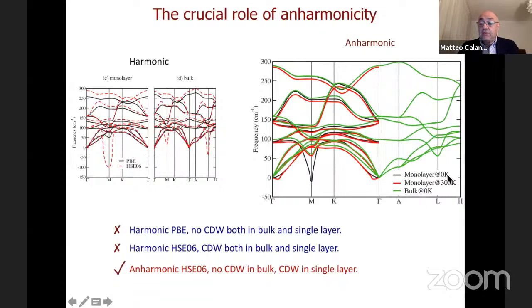As you can see here, the monolayer at 0 Kelvin still has a slightly imaginary phonon, and the bulk at 0 Kelvin has no instability. So actually, the thickness dependence of the charge density wave in the system is entirely due to anharmonicity. So this suggests that the classical theory of Peierls distortion, in which, due to the nesting condition of the electronic structure, you have a strong energy gain by the distortion, should be reconsidered, because there are two effects that are not considered. One is the electron-electron renormalization of the electron-phonon coupling, and the second one is the fact that anharmonicity is a huge correction and has a tremendous effect on the phonon.